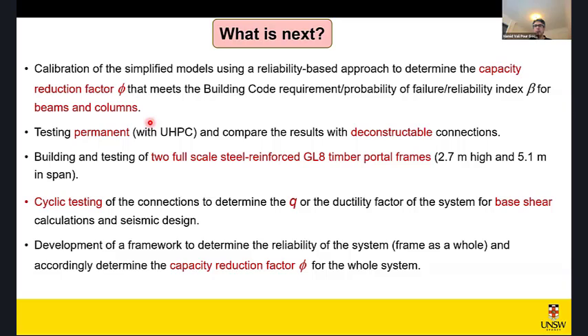Certainly. And that was essentially the reason we decided to go down that path, because we want to be very quick. We don't want to wait another week or so for the concrete to cure, and then we could go for the next level. We wanted to do it just bang, bang, bang, one after another very quickly. And after 48 hours, it gets to 72, 73 MPa, right? So it gives you the window for assembling and putting the story above that. Again, you could easily imagine a 5 or 6 story building being made out of GL8 timber being constructed very quickly with no brace bays at all. That would be an incredible opportunity for our whole industry.